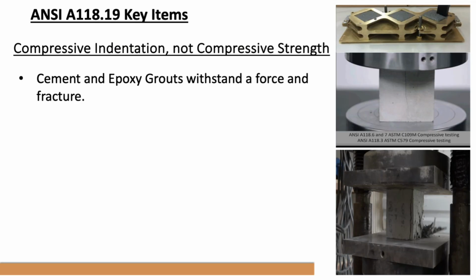So the testing that we did, for compressive indentation, not compressive strength. Cement epoxy grouts, it's a different test. They have a force and fracture test. As you can see on the right, they have two cylinders that are pushing down, creating compressive strength until the grouts crack, and then it gives them a reading of how many PSI it took to crack that.